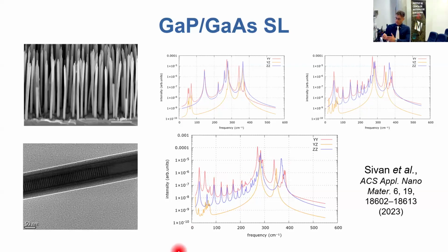Then the modification of the superlattice period, so introducing more and more atoms in the primitive cell of the superlattice, introduces more peaks. It also slightly shifts the principal peaks from their position, but it introduces more optical frequencies. You can really see that the longer the period gets, the more peaks you get, meaning different phonon modes and optical frequencies.